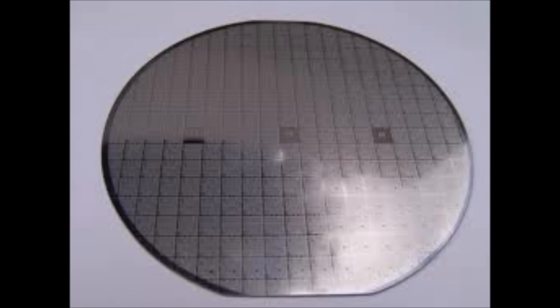For example, the Temescal, that's the unit on the firewall. That's an electron gun deposition system. And it deposits dielectrics. So we have two sources. We have a silicon oxide and a titanium oxide. And we do them in sequence. Boom, boom, boom, boom, boom. Do seven of those in sequence on the top surface. So we've already done the oxidation underneath. And then this goes as the final step on the top. And that creates the optical cavity.